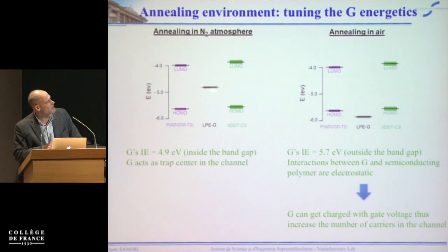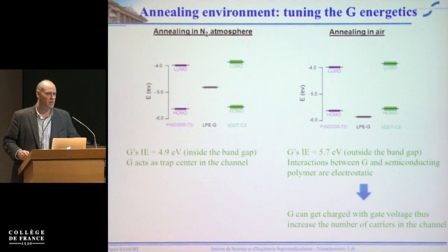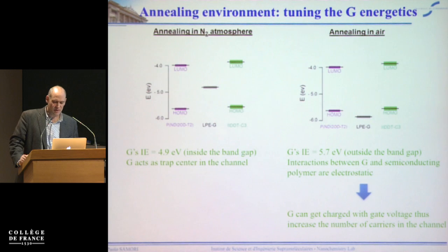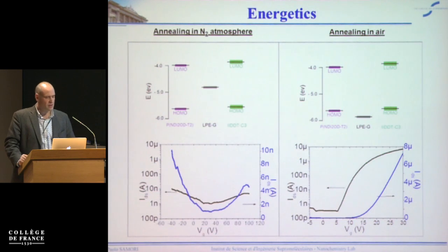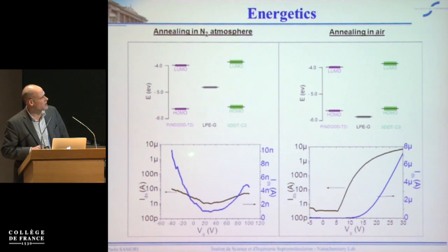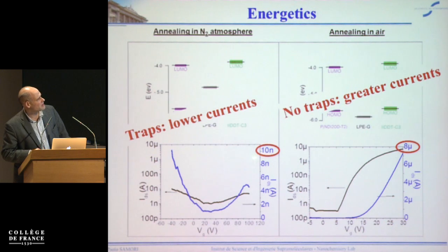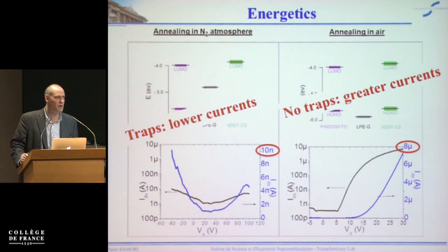Now, what is the situation? Here we have a level of the graphene that is within the band gap. If the level of graphene is within the band gap, it acts as a trap for the charges of the semiconducting polymer. Whereas in this case, when the level is out of the band gap, the interaction between the graphene and the organic semiconductor is purely electrostatic. So essentially, the graphene can get charged with the gate voltage, and we can use this to increase the number of charges in the channel. Here we have some traps, here we don't have traps, and this is reflected by the fact that here we measure some nanoamp current, and here, with no traps, we measure some microamp currents.